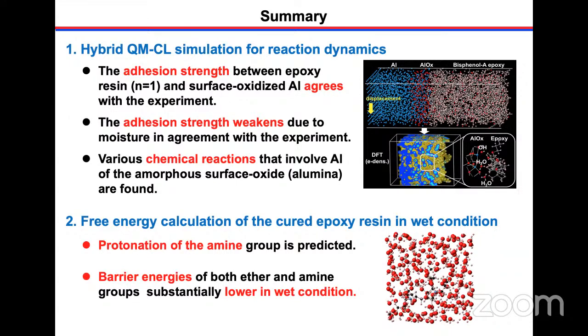Part B is for the free energy calculation of the cured epoxy resin in wet conditions and also in dry conditions. Then we have found that in one of the three amine groups, the protonated state is stable. Because of that, in wet conditions, barrier energies for the ether group and the amine group become substantially lower. Then this enhances the breaking of the cured epoxy resin in wet conditions. So thank you very much for your attention.